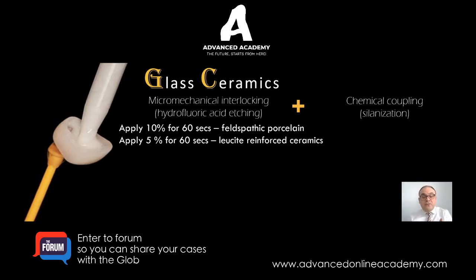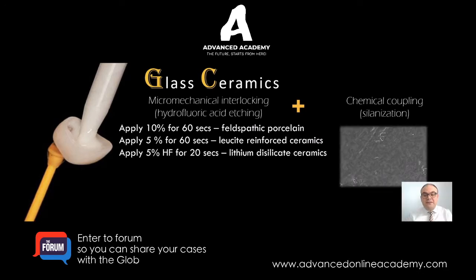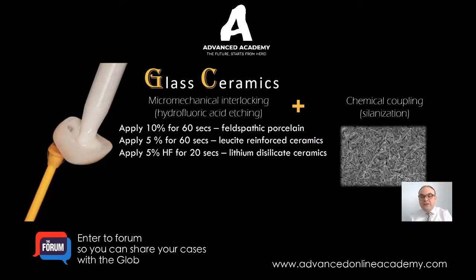Leucite reinforced ceramics like the Empress system, 5% hydrofluoric acid for 60 seconds. Lithium disilicate or e.max, a very popular ceramic, is 5% acid for 20 seconds. That's it. This is a scanning electron microscope image of the lithium disilicate surface before etching and then after etching. You can see and appreciate how these micro gaps are formed to enhance the micromechanical bond to the tooth structure.